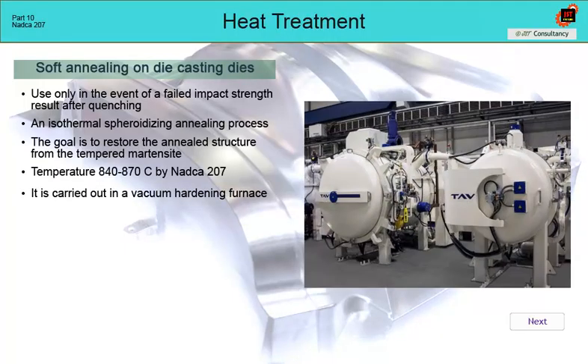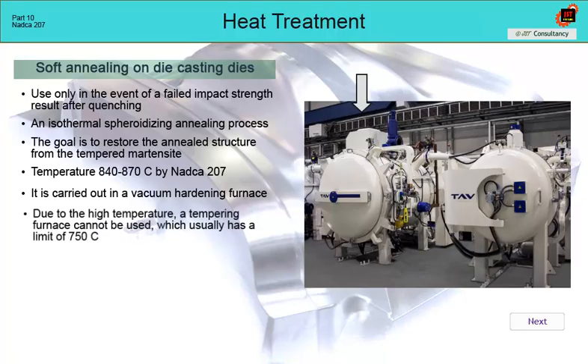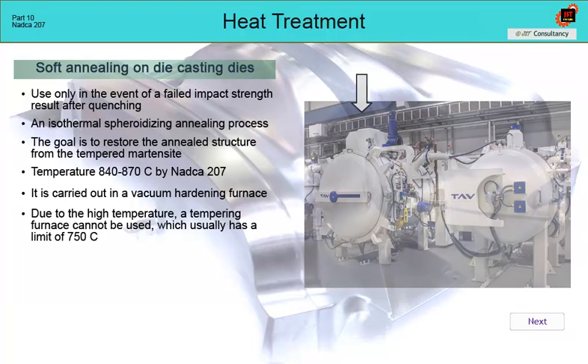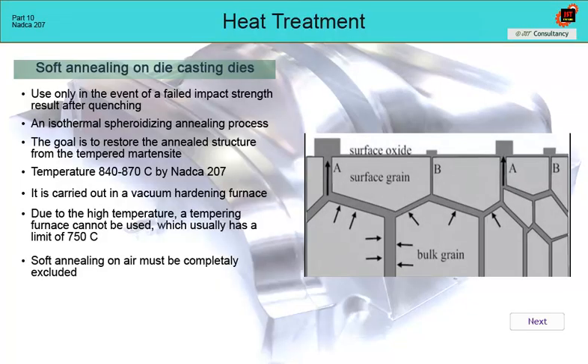Since heat treaters that perform vacuum hardening of die casting inserts usually do not have a different type of furnace than vacuum furnaces, it is necessary to carry out the annealing process in a hardening furnace, taking into account the temperature. Soft annealing in air must be completely excluded. There would be irreversible damage to the structure of the material by decarburization and oxidation to a great depth.